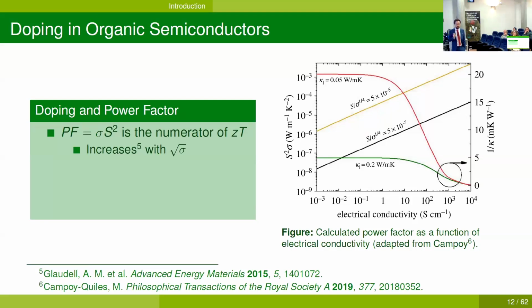So how does doping affect the thermoelectric efficiency of organic thermoelectrics? Let's talk first about doping and power factor. The power factor is sigma times the Seebeck coefficient squared, and is the numerator of the dimensionless figure of merit. It has been found empirically to increase with the square root of the electrical conductivity, which you can see here in this nice graph from a focus article of Mariano. Thank you.